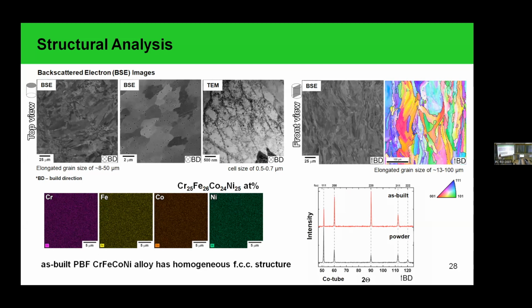And those black dots in the BSE image, are there nitrogens? Yes, we recognize them as oxides or pores. In addition to nitrogens, you mean? Yes, you have nitrogen, oxides, and pores. The formation of oxides is typical for the additive manufacturing technique, because even with a small addition, we observe oxides in the as-built state in any materials. So it's essential for this material. And yes, we have small precipitates of oxides or carbides in our materials.